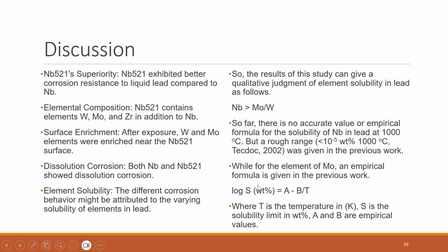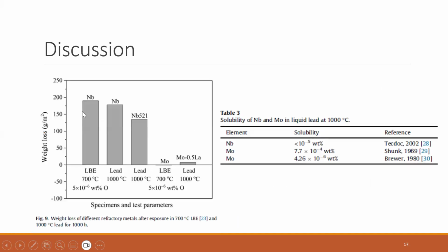like this: log S wt% equals A minus B per T, where T is temperature in Kelvin and S is the solubility limit in wt%, and A and B are empirical values. And this figure 9 is about weight loss of different refractory metals after exposure in 700 degrees Celsius LBE and 1000 degrees Celsius for 1000 hours.